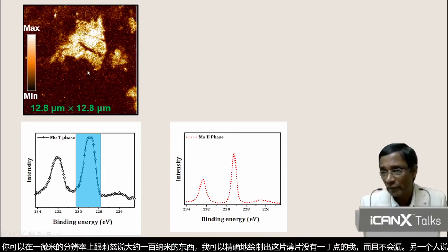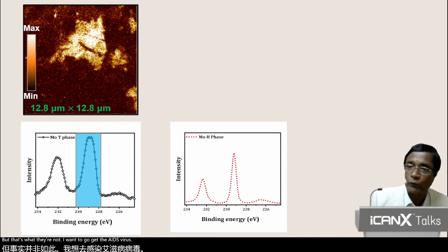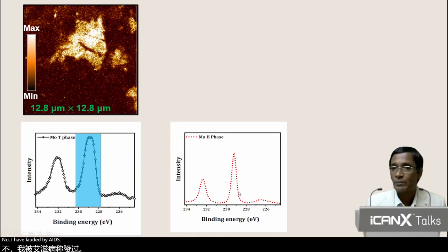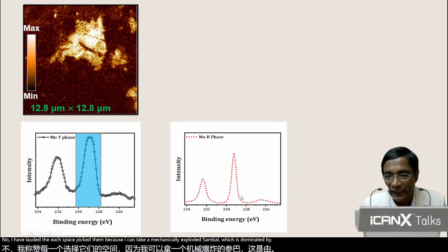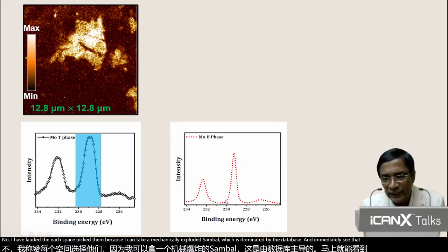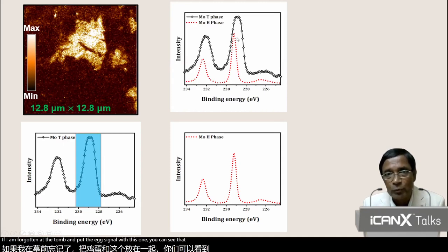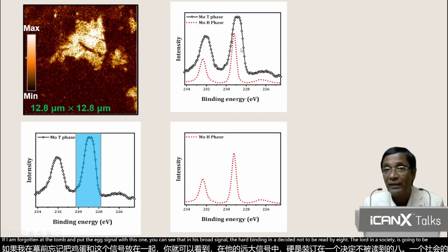But that's not enough. I want to know where the H phase is and where the T phase is. Now, I've plotted the H phase spectrum because I can take a mechanically exfoliated sample, which is dominated by the H phase, and immediately I see that it's a very narrow signal compared to this broad signal. If I compare the two and put the H signal with this one, you can see that in this broad signal, the higher binding energy side is contributed by H, the lower energy side is contributed by, as I know from my earlier experience, T phase.